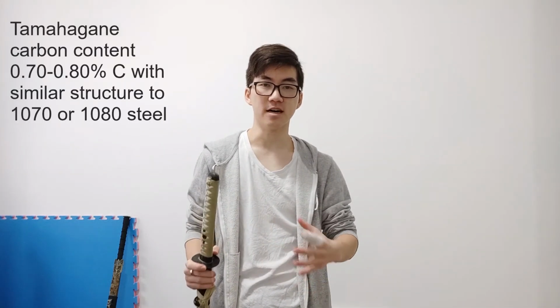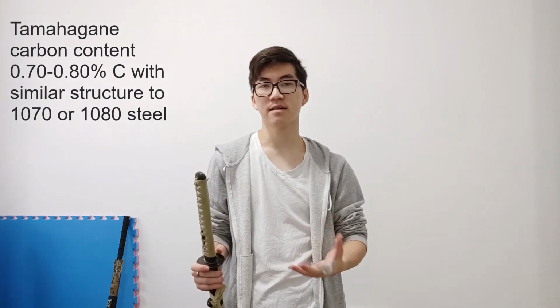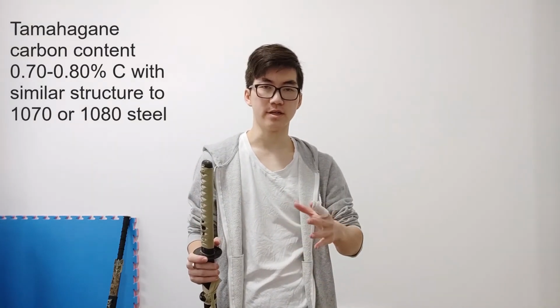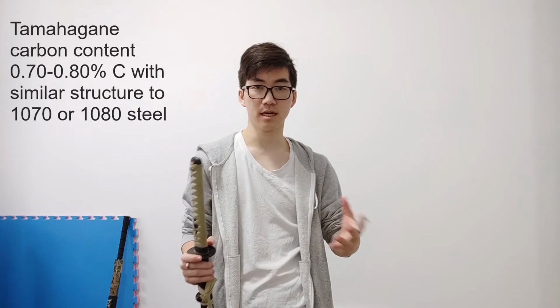And the thing is that when you look at ancient tamahagane, they've done structural analysis of it, and it comes out to be about 0.70 to 0.80% carbon. So here you started with a lower carbon steel, a 1060 steel, and then you folded it and reduced it even more. So your folded steel is worse than your ancient quality swords.